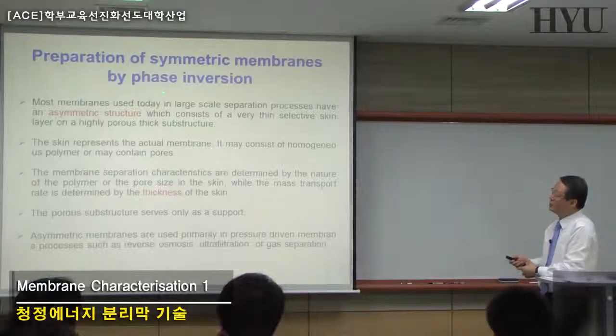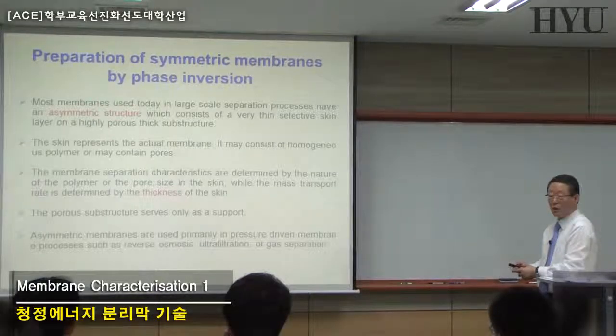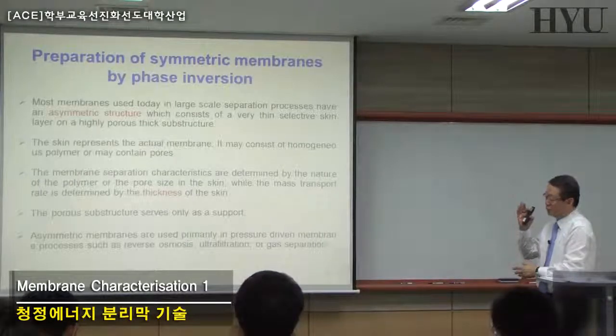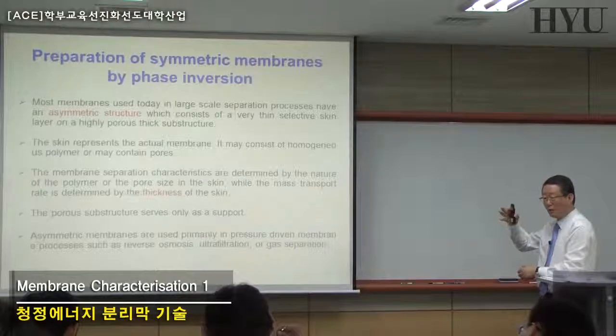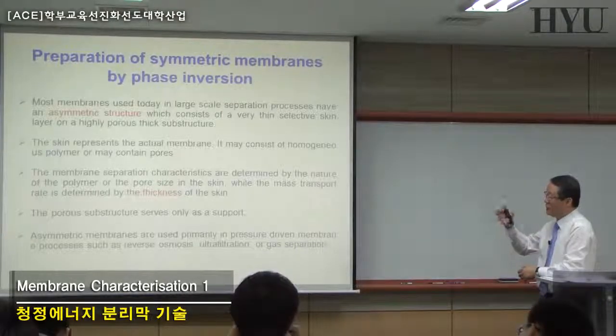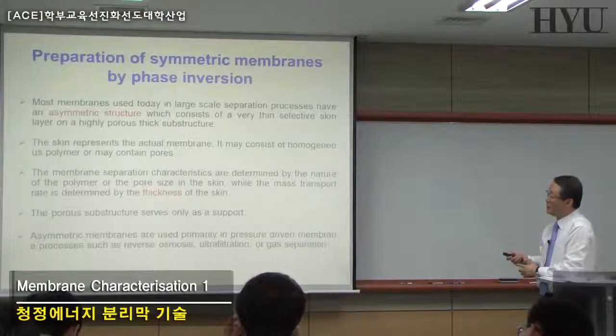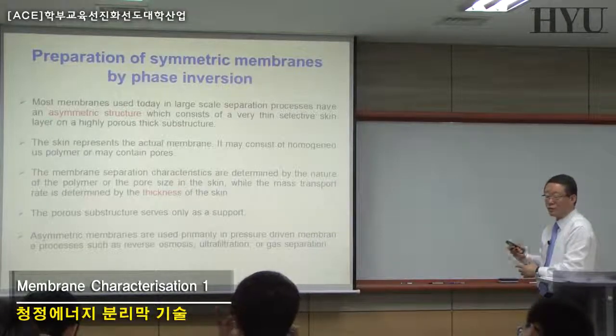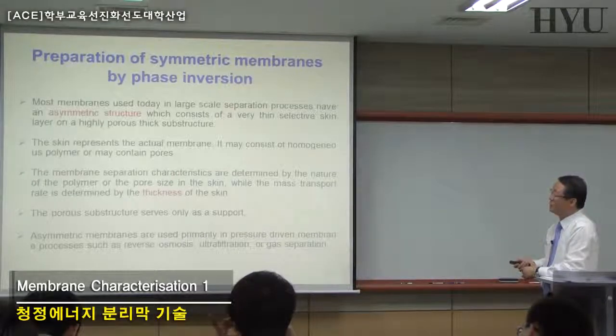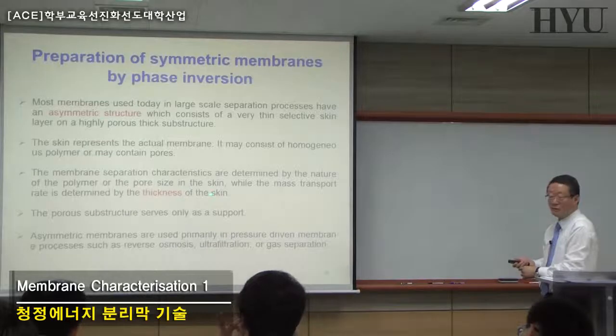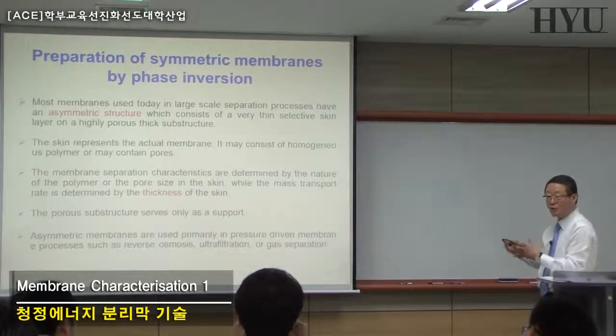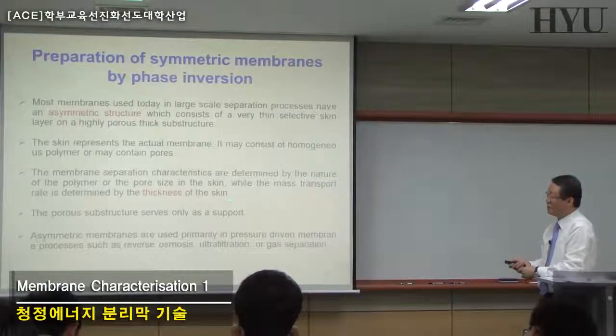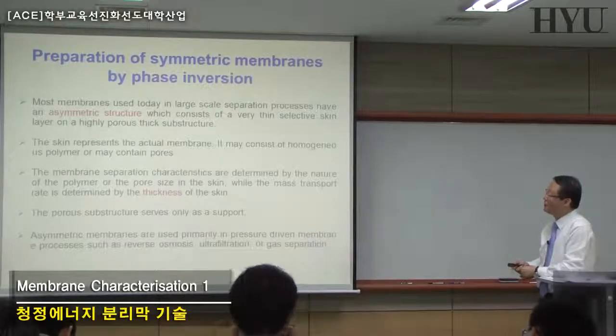By using this phase inversion, we can make not only symmetric structure, but we can make asymmetric structure as well. In other words, we have a very thin layer on the top and a porous structure on the bottom, and that's what we call the asymmetric structure. We can make a hollow fiber, we can make an asymmetric flat sheet membrane, and so on. The skin is the selective layer. This is the separation-determining layer of the membrane, and it's very important. The presence of this skin is what we call the membrane. Otherwise, you can call it a film.